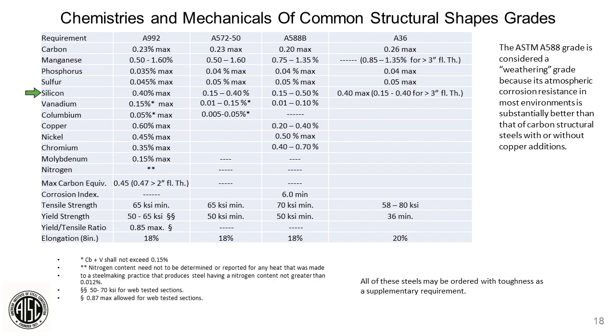Now the next one is vanadium. That's our microalloy addition. A little bit of vanadium goes a long way. Same with columbium. Doesn't take much to have a dramatic impact on the properties. So you look at these, they're pretty low numbers: 15 max, 10 max, 5 max. So very little additions of these make a dramatic impact on the properties of the steel.